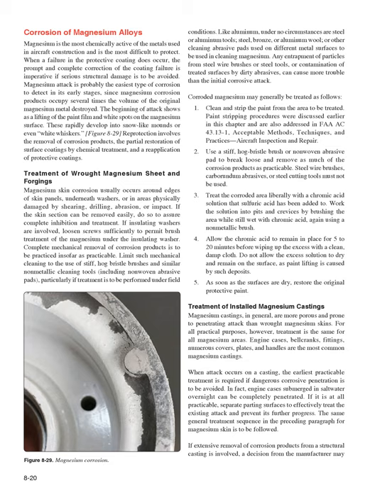Magnesium attack is probably the easiest type of corrosion to detect in its early stages, since magnesium corrosion products occupy several times the volume of the original magnesium metal destroyed. The beginning of attack shows as a lifting of the paint film and white spots on the magnesium surface. These rapidly develop into snow-like mounds or even white whiskers. Figure 8.29, reprotection involves the removal of corrosion products, the partial restoration of surface coatings by chemical treatment, and a reapplication of protective coatings.